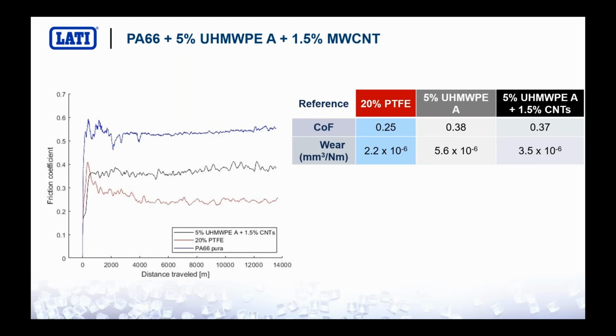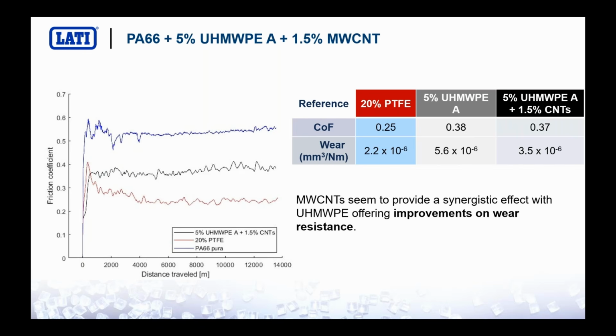Now let's take a look at the synergic effect between the ultra-high molecular weight polyethylene type A and 1.5% of carbon nanotubes. As you can see, no effect as far as the friction coefficient is concerned, which remained more or less the same as the version with only ultra-high molecular weight polyethylene. But from a wear point of view, we saw a small improvement, which was good. So this is another possible candidate.